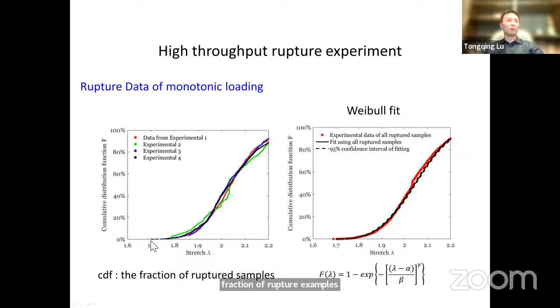For example, if you apply a stretch of 1.9 something, the CDF is 20%. It means 20% of the 1,000 samples have ruptured at this stretch. So CDF just means the fraction. After collecting all the 4,000 data points, we can do a Weibull fit and obtain some fitting parameters. We will talk about the fitting in detail later.